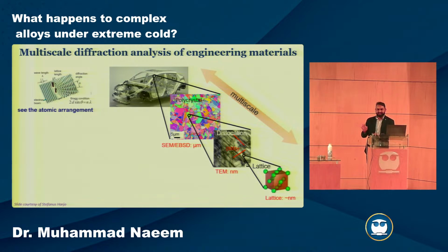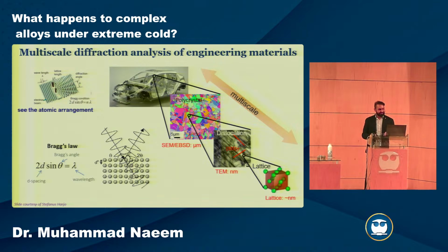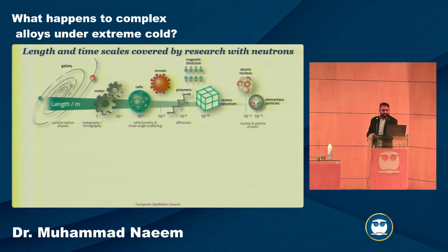equal to n lambda. So basically it's two things, which is you have some radiation, in this case X-ray for example, and you shine it on your material, and then you want to measure lattice spacing, how far apart these planes are from each other. And from there, we can see a lot of properties. So this is the same thing, and what we are after is lattice spacing or d-spacing, and that's the one thing which we get through diffraction. Okay, so I have been doing mainly neutron diffraction, and I will be saying a lot of good things about neutrons today.